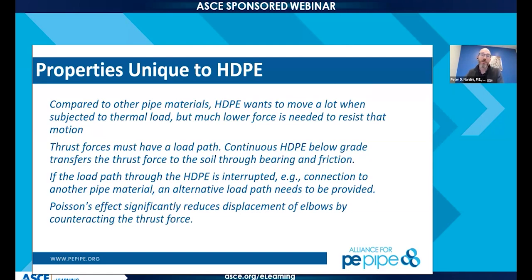And I think the major takeaway that we hope folks have is if you let the HDPE move, it wants to move quite a bit, but really it takes a pretty low force to restrain it. And so, from a design perspective, if we have a long run of HDPE pipe subjected to a thermal load, we should really think about restraining it. The force may not be that significant. If it's just a short run of pipe, maybe the displacement can be accommodated.